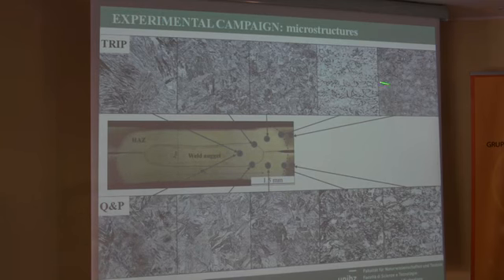And so in the upper figures you can find the evolution of the microstructures of the TRIP steel coming from this point to the weld nugget, and similarly you can see also the microstructure variation of the quenching and partitioning steel.